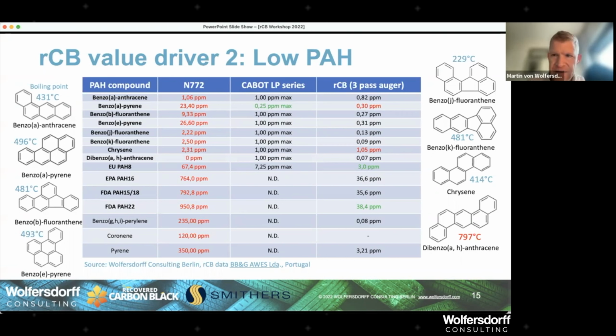To close that slide, and then we go on a break. All these components, I'm showing here the group of 8 left and right, group of 8 polycyclic aromatic hydrocarbons with their boiling points. And there's one compound, benzo[j]fluoranthene, which is already evaporating at 229. The rest is evaporating beyond 400 or close to 500, and then it makes sense that most pyrolysis reactors, kilns, are run at 550 to 600 or even 700 degrees.